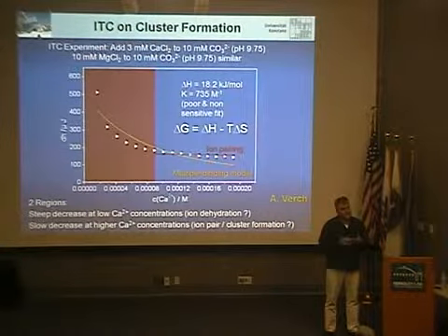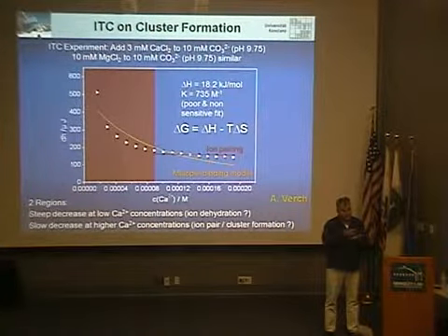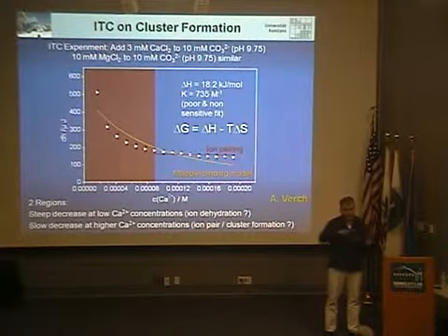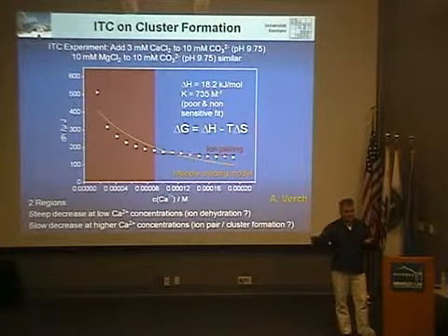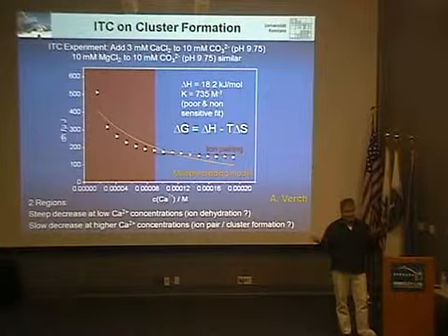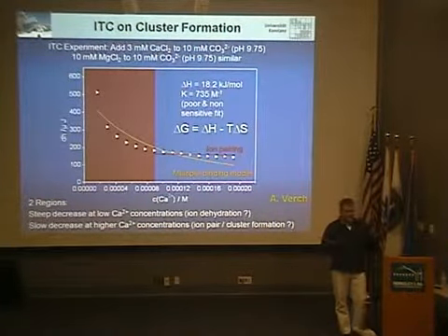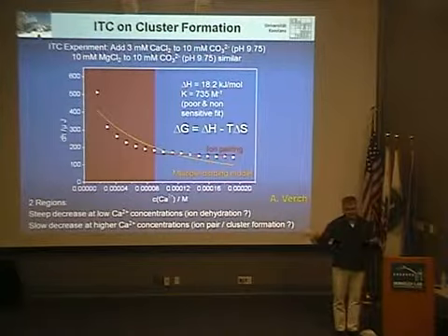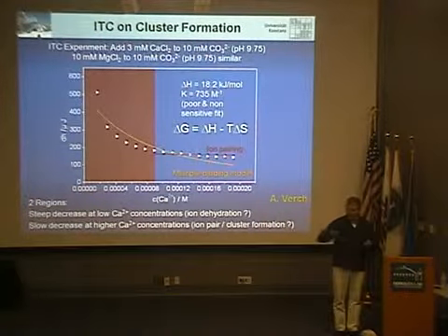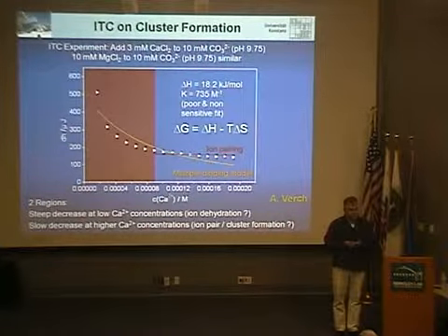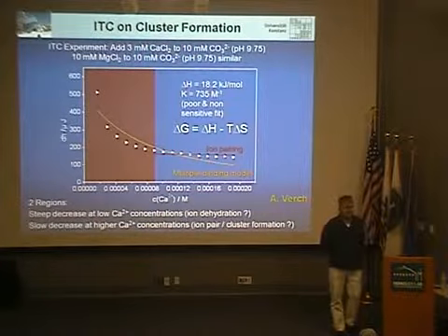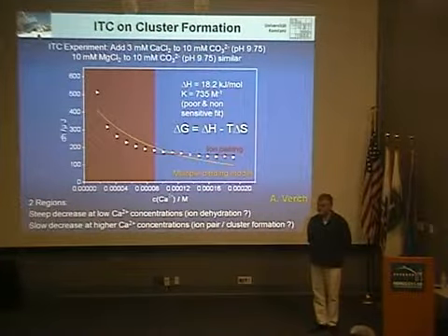But once they nucleate, you have the amorphous phase, then you get this constant region of the curve after the nucleation point. That means ions must attach to the surface because the concentration of ions stays constant. As you know it from the textbook, it's a solubility product, and it stays constant all the time. That means everything you add must be incorporated into the solid precipitate, whether it's crystalline or amorphous. I absolutely agree.